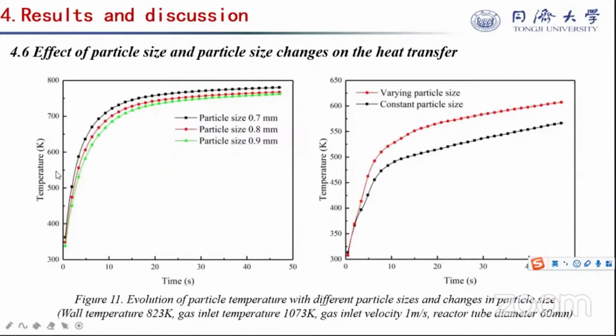The left figure examines the particle size effect on the heat transfer. It can be seen that the smaller the particle size, the faster the temperature rises. The reason is that with smaller particle size, the bed porosity and the gas velocity will increase accordingly, which will enhance the heat transfer.